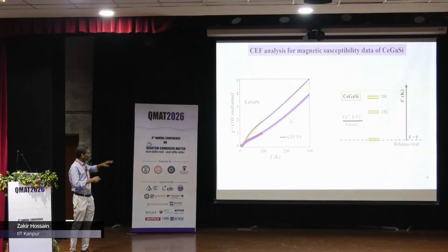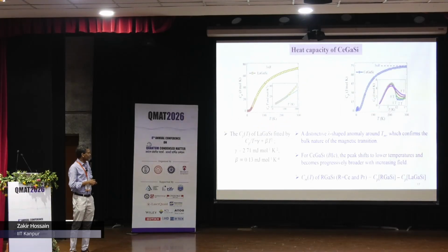And from the magnetic susceptibility analysis, we propose this level scheme, which can actually be directly checked using inelastic neutron scattering. Neutron scattering will be able to further confirm whether this proposed level scheme is all right or not. But within whatever data we have, this is consistent with the heat capacity data. So heat capacity also confirms the magnetic ordering. Okay, we measured down to 2 Kelvin. Maybe further low temperature will give even better.